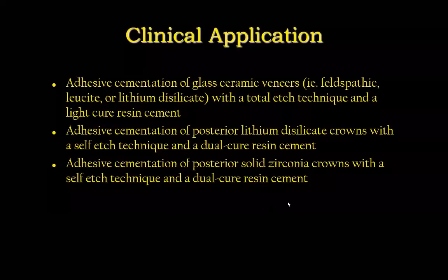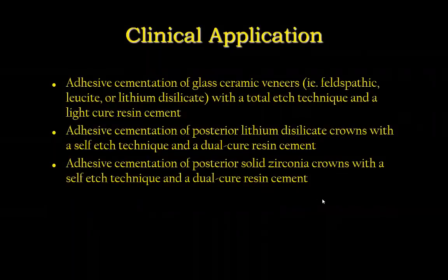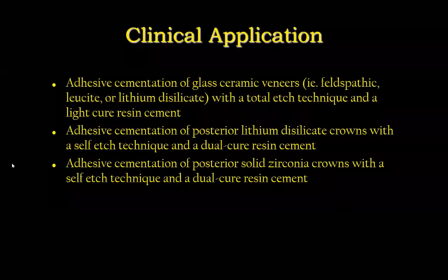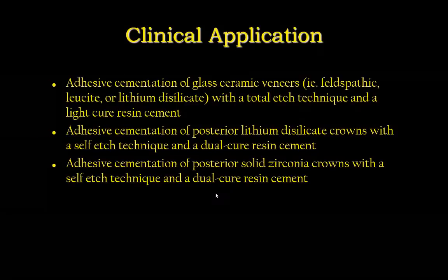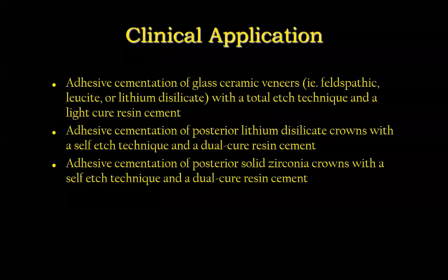And then we have our adhesive cementation of solid zirconia crowns with a self-etch technique and a dual resin. The same thing. The difference is how you treat the restoration. That's the only difference. You treat the tooth exactly the same way. Our universal adhesive, light cure, evaporate the solvent, light cure. However, zirconia, as I said a minute ago, you have to clean it with something like Ivaclean or Zirclean by Bisco, okay? You have to clean zirconia.